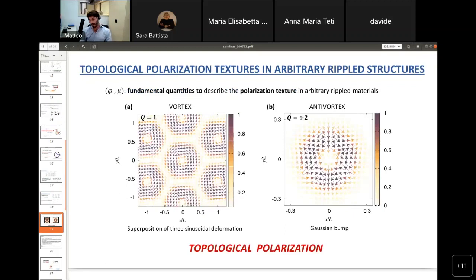Now, the example that I just presented is a peculiar case of a more general consequence. Indeed, we recently realized, and this is a really recent result because we realized it just last week, that the quantity considered is very important to describe the polarization texture, that is in general the polarization field within the material of arbitrary rippled structure. Indeed, we find that even when the curvature is not uniform but is, for example, changing in space, that means having a local curvature, the quantity that we study can still be used to derive the polarization field.